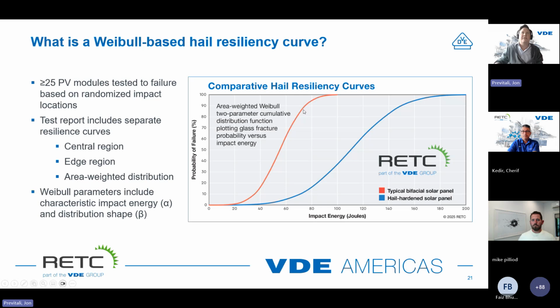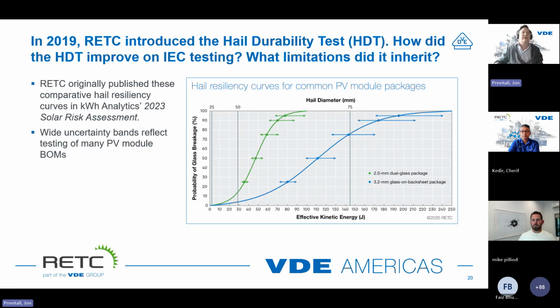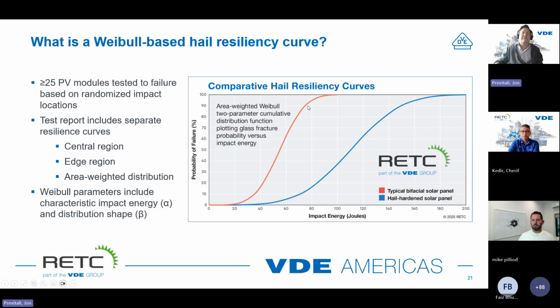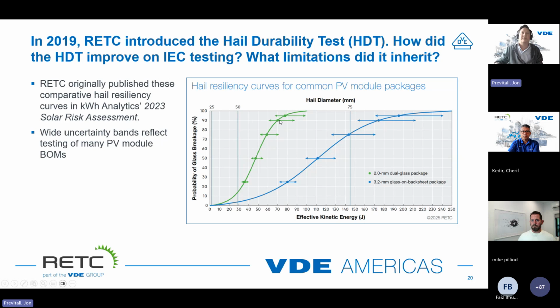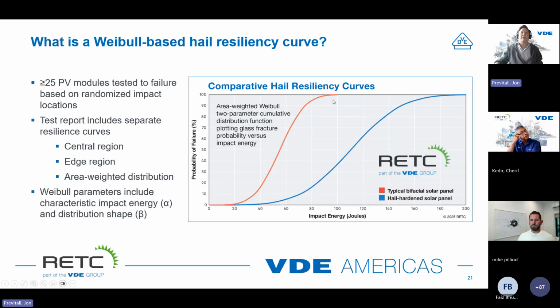So they're in the same shape as the curves that Sharif was talking about before, but they don't have the same level of uncertainty. So we don't have these large uncertainty bars anymore. So these are much more accurate depictions of the probability of failure based on impact energy, or freezer ice ball size, or naturally occurring hail size. We can essentially translate the impact energy into those other units for modeling purposes.